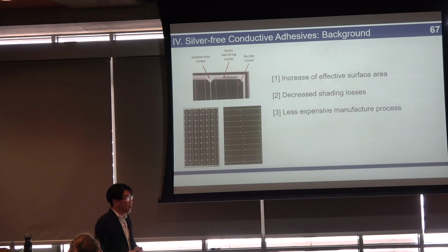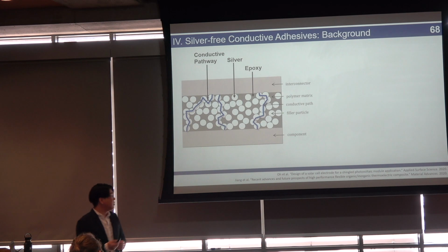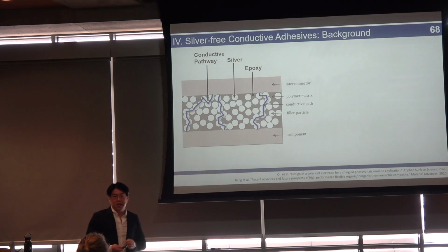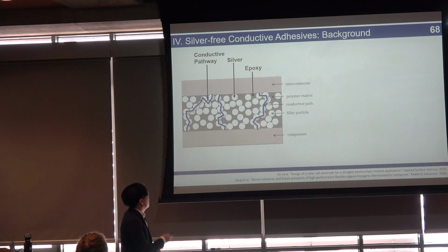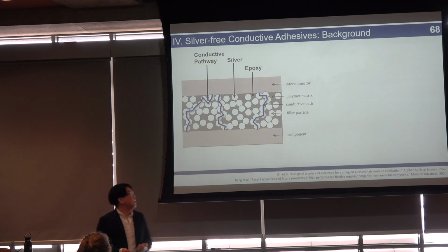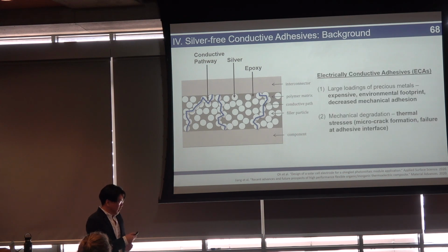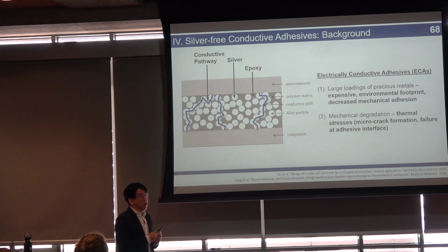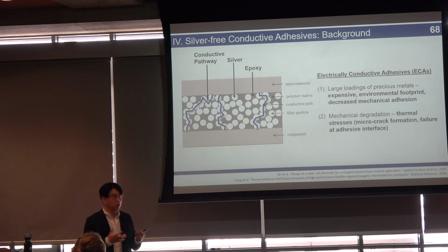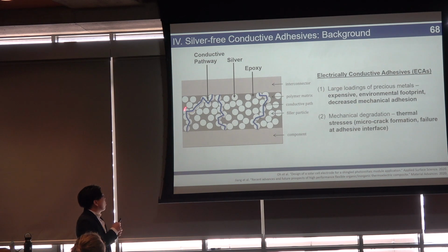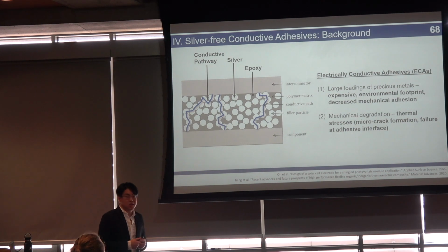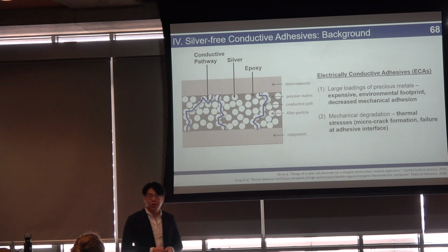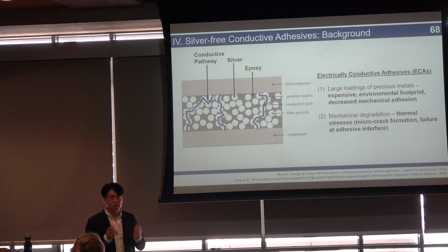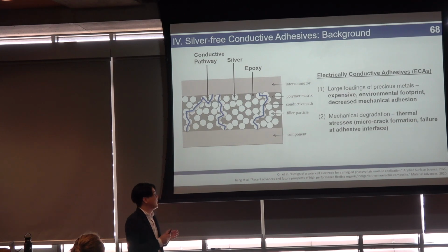So we talked about the energy payback time. This sort of ties into that. So the things that we use to glue together these solar panels are called electrically conductive adhesives. And what they're made of is silver particles that are encapsulated in epoxy. So it's basically a plastic glue that's filled with silver. And the silver, of course, creates a conductive pathway, but this leads to a couple different problems. First and foremost, you need about 70 to 80 weight percent silver. That's a ton. That's a lot. So it's very, very expensive.